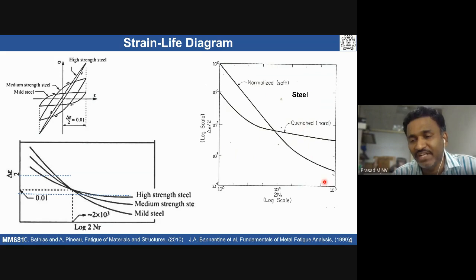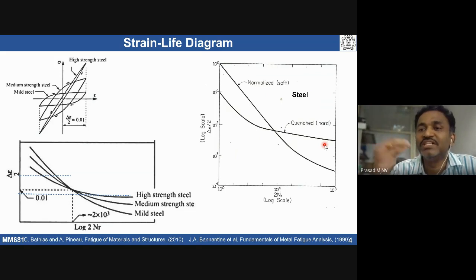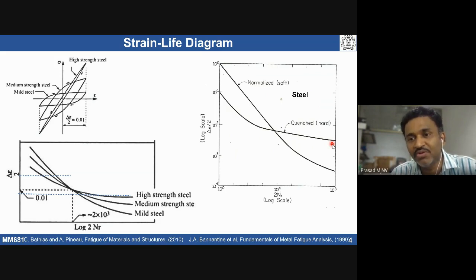When you talk about high cycle fatigue, we need to apply a higher strain amplitude or stress amplitude, and only then do we see the crack initiate, because we already discussed that the period for crack initiation is more than crack propagation in the high cycle fatigue regime. So in the case of hard materials, we need a higher stress to initiate a crack. If you apply this much stress, it might not be sufficient to initiate the crack. We'll talk about why even within elastic deformation we do see crack formation. That will be discussed down the line.